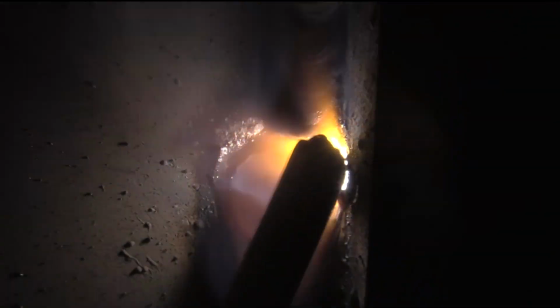140 amps still, hadn't changed the amperage a bit. In fact, the amperage will just stay at 140 for this Z-weave pass here, as well as the stringers. And part of that is just temperature of the part. We didn't let it cool off much, just a few minutes to wire brush it and reset cameras and things like that. Temperature of the part does affect amperage by a little bit. Sometimes you can turn the amperage down a little bit if things are getting really hot. Again, if you're starting off and it's cold, maybe you might need 5 more amps.